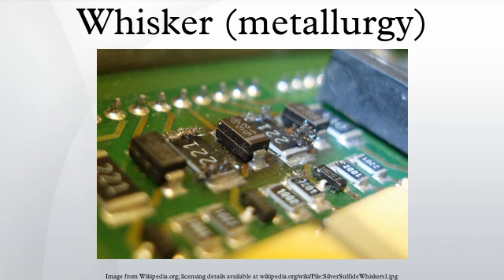Metal whiskers form in the presence of compressive stress. Zinc, cadmium, and even tin whiskers have been documented. Many techniques are used to mitigate the problem, including changes to the annealing process, addition of elements like copper and nickel, and the inclusion of conformal coatings. Traditionally, lead is added to slow down whisker growth.